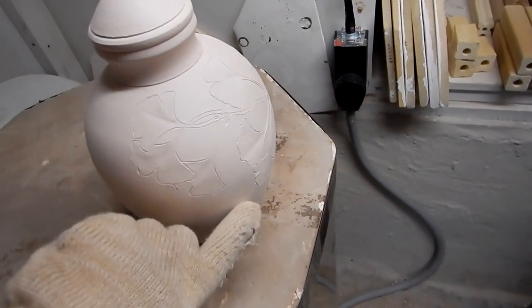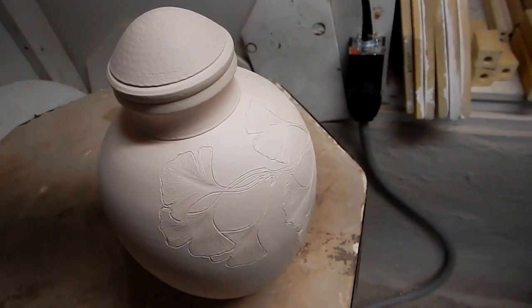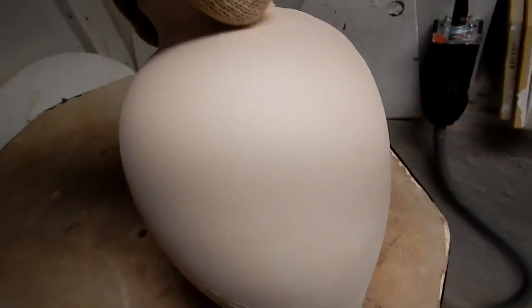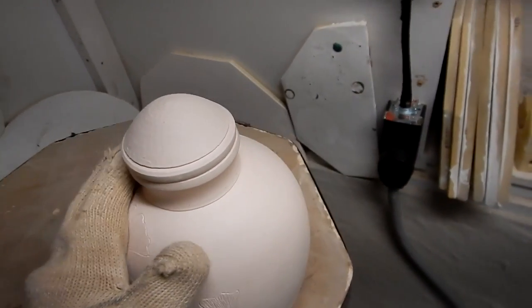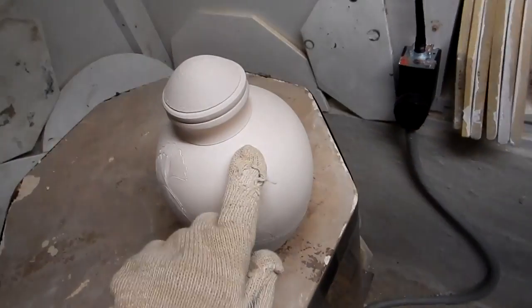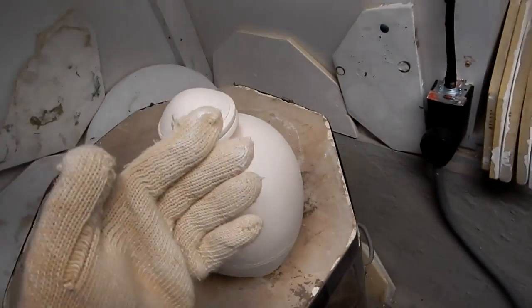These look okay too. So what I'm looking for is the dreaded pop-out. What a pop-out is — if you burnish or smooth out something like Raku clay, which has just an inordinate amount of grog in it so it can take the thermal shock of quenching or doing whatever you're going to do quickly in Raku — some of the grog has little pieces of metal or just foreign bodies in it, and sometimes it'll literally make a crater pop out in the firing. Usually in bisque firing, because this is about as hard as this clay is going to get at cone 04, just below the 2000-degree mark at 1940-ish.